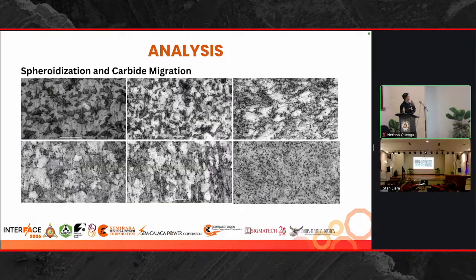So here are some of the micrographs or the replicas that we have acquired during the field, and it shows the microstructure evolution. So we have here, this is like the healthiest microstructure that I can find in our data. So as we can see here, the carbide grains are still intact, and as we go through, this carbide starts to agglomerate, they start to coarsen, and they start to disperse out of the microstructure until it reaches this point where the spheroidization and the carbide degradation is complete.